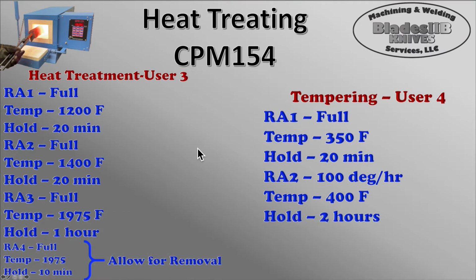Same thing, I'm going to put my blade in the freezer for several days before I do my first tempering. And sometimes after I temper it the first time, I'm going to go put it in the freezer, let it sit in there for 2 or 3 days, and then come back before I do my second tempering. A lot of people do a cryo freeze using liquid nitrogen. I don't keep any of that on hand, so I'm just using my home freezer. And again, been having pretty good luck with this recipe for my CPM154. So let's go back down to the kiln. Let's get this programmed in here for our heat treatment, and let's go ahead and fire this blade.